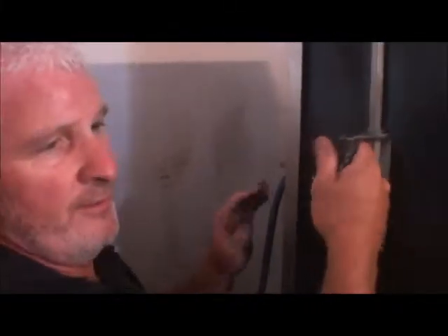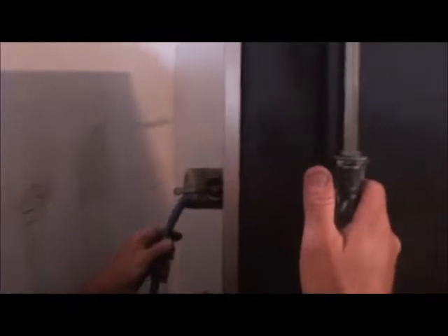Okay, what's this next step? Okay, this next step is we ran the vacuum line through the exhaust port on the oven. And we reconnected the vacuum line. So now we're going to close the oven door, and we're going to set the oven at 200 degrees Fahrenheit. Okay, there's the vacuum pump connected to the hose, which goes into the oven, which keeps it under vacuum while it's curing.